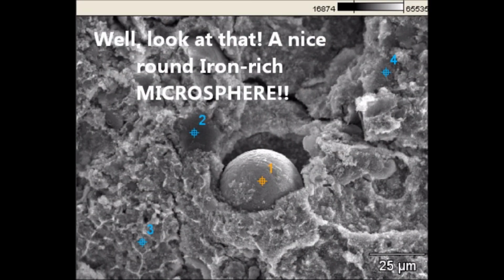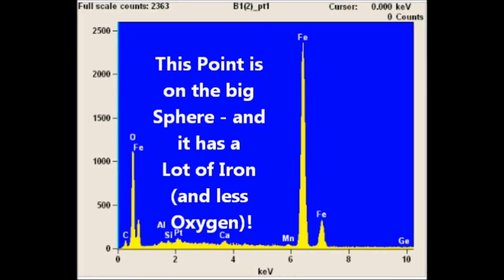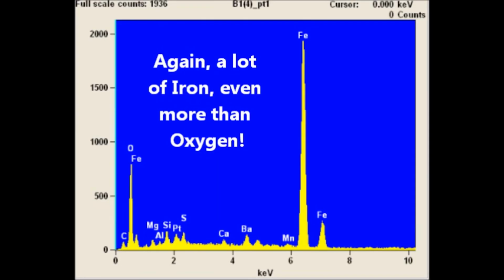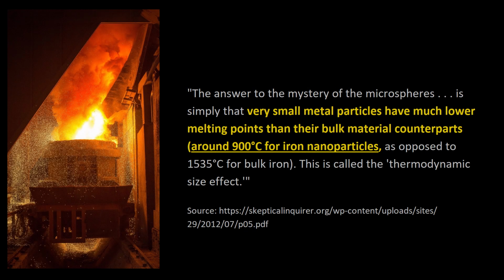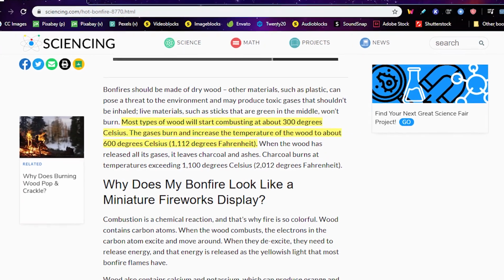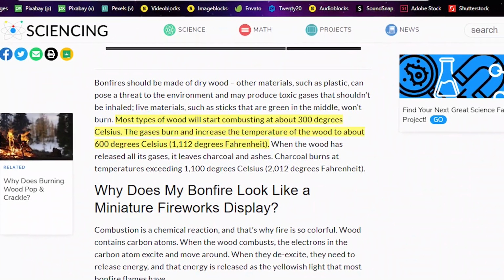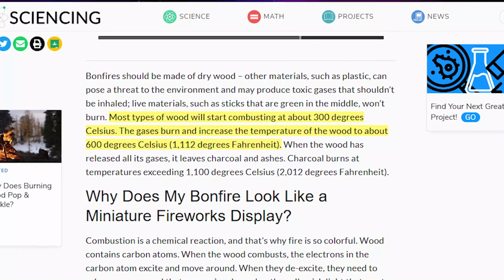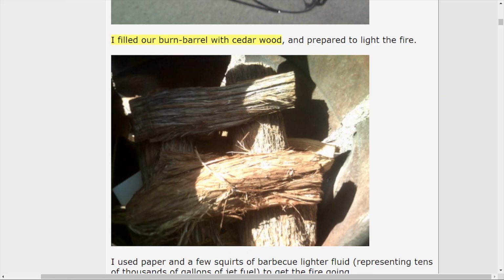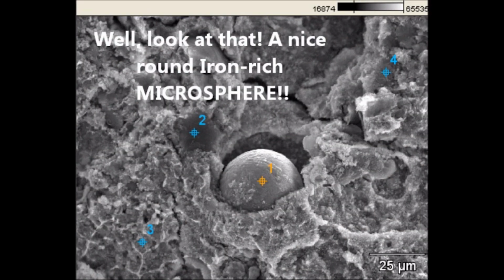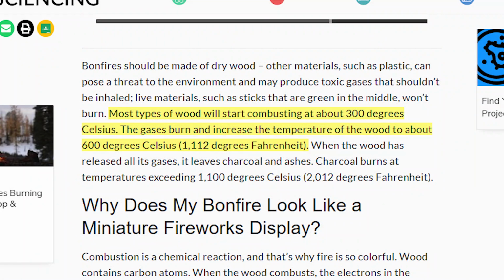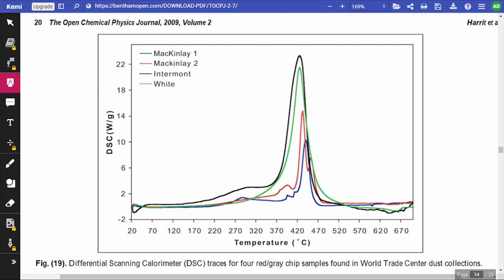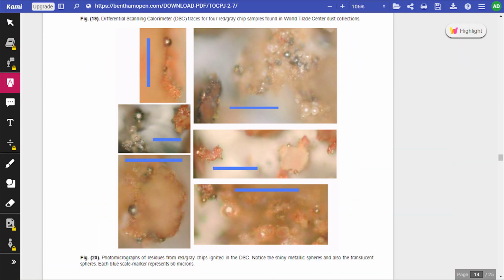Here we see two such spheres that were created, along with their EDX spectra showing that they are indeed primarily made of iron. Thomas says that the melting point of iron nanoparticles is around 900 C, but his own experiment seems to show that it might be even lower than this, given that wood fires range between 300 and 600 C, yet in his experiment, a wood fire was hot enough to create iron microspheres. The temperatures reached in wood fires are also comparable to those reached in the Harrit et al. DSC tests. So I see no need to invoke thermite as our explanation for how these microspheres formed.